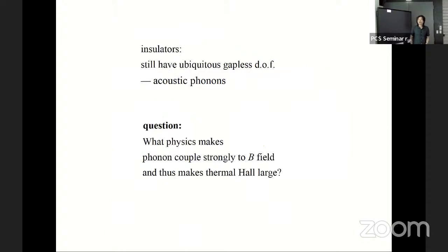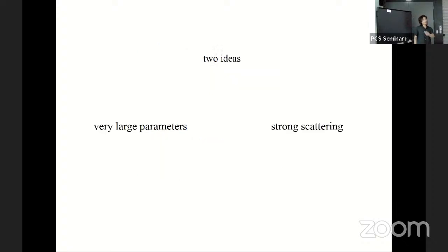Okay? So the question now becomes, what physics makes phonons couple strongly to the magnetic field, even though they are neutral, so that they can make the thermal Hall very large? And of course, we can have two vague ideas. The first idea is, maybe there's some very large parameter in the material, so that even though you expect the effect to be small, due to a very large parameter, it turns out to be large. And the second is maybe the phonons strongly scatter with some other degree of freedom. Phonons themselves may not couple that strongly to the magnetic field, but maybe they also interact with some other degree of freedom, which helps the process somehow. So those are two directions of thinking.